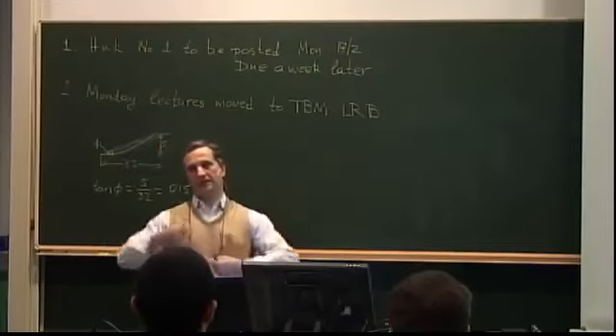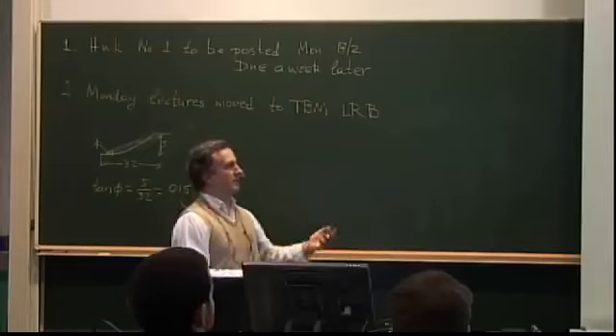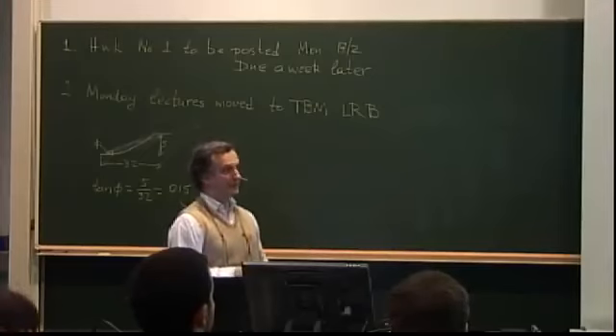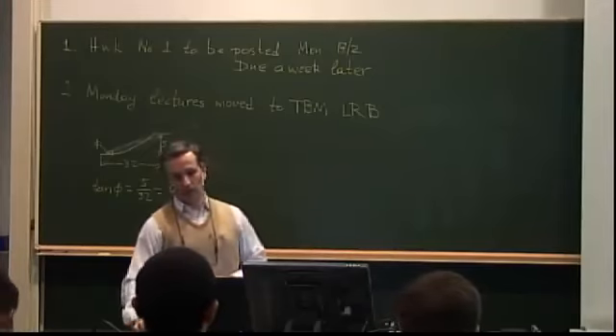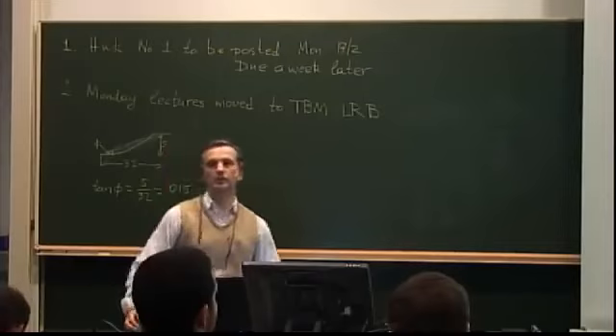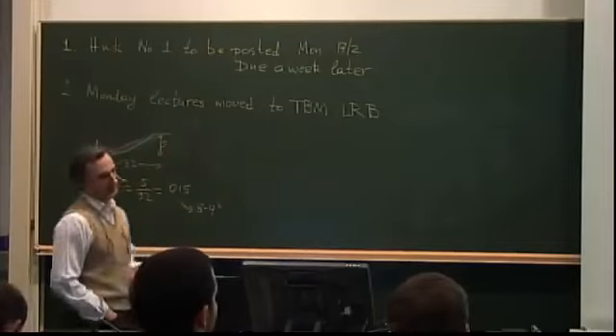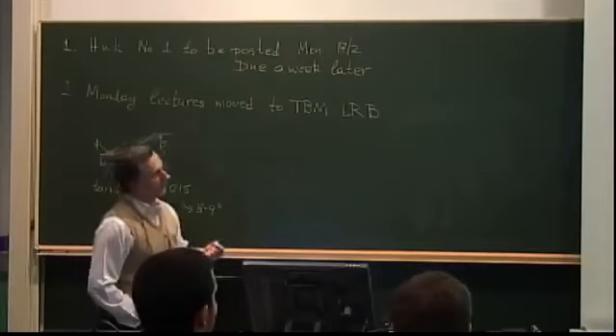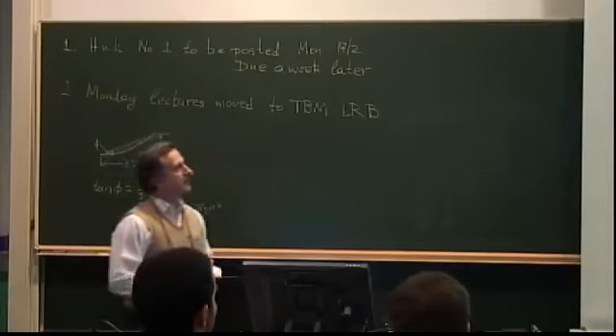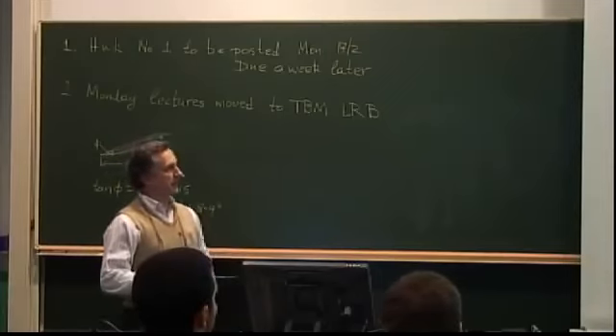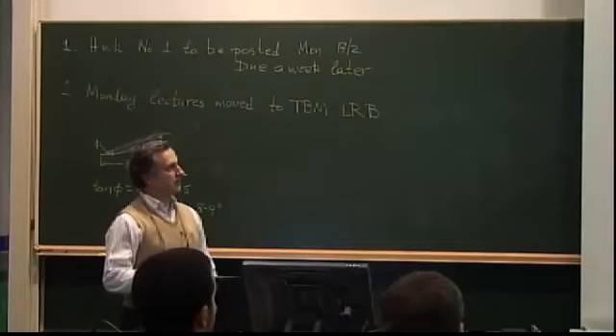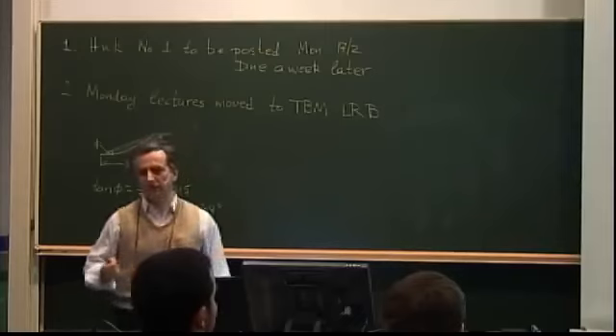So this is to show that even though the criteria agree with each other reasonably well, they might not be close to what the actual specimens would do. And recognizing this problem, many people have tried to compare actual test data, shown here, with different criteria. And this is a gentleman called Edge from England, John Hart-Smith, which is a guy I need to introduce right now, and Puck, which is probably the best criterion we have today.